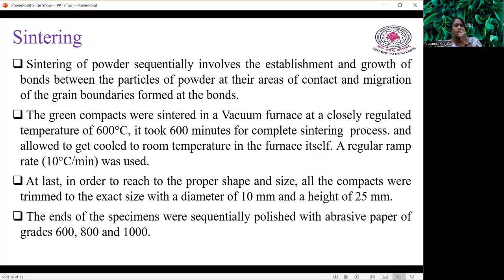The sintering of the powder sequentially involves the establishment and growth of bonds between the particles of powder at their areas of contact, and migration of the grain boundaries formed at the bonds. The green compacts were sintered in a vacuum furnace at a closely regulated temperature of 600 degrees centigrade, which took 600 minutes to complete the sintering process, and it is allowed to cool to room temperature in the furnace itself. And then we could get some specimen sizes, and the abrasive paper grades of 600, 800.